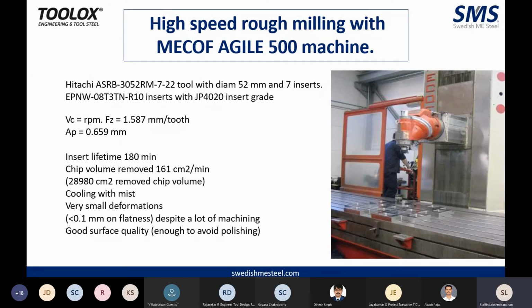Even after this extensive removal of chips, you will find that the deformation is very, very low, less than 0.1 mm on flatness. And it provides you an excellent surface quality, just enough to avoid polishing.